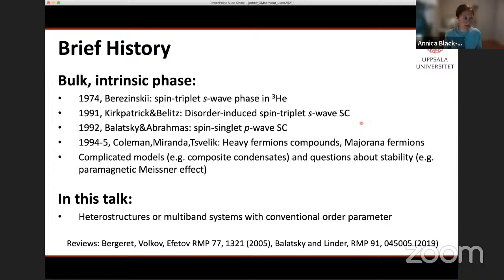It's an intrinsic superconductor. It's proposed to be an interband pairing mechanism. It has a lot of odd frequency, in fact the odd frequency is dominating in this material. And it turns out that the Meissner effect is actually not paramagnetic, but the odd frequency actually drives the diamagnetic Meissner effect. So to me, it could be a possibility to go to topological band structures, multiple bands that are topological, and then you can possibly get around this paramagnetic issue. So that could be a way forward to actually think about intrinsic odd frequency superconductors.